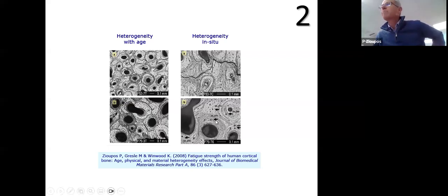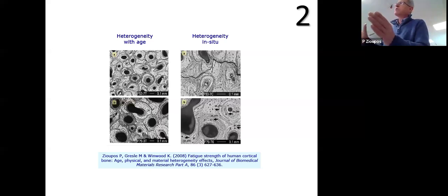So here, for instance, we have some microhardness values of the various elements in bone, and it has been published, of course, but you can have hardness of 44 up to 56, depending on what type of bone tissue you tap at any point. So really, what bone tissue is with age is a mosaic of tissue age elements, and the more heterogeneity and variability you've got, the more brittle it will become, inevitably, right?